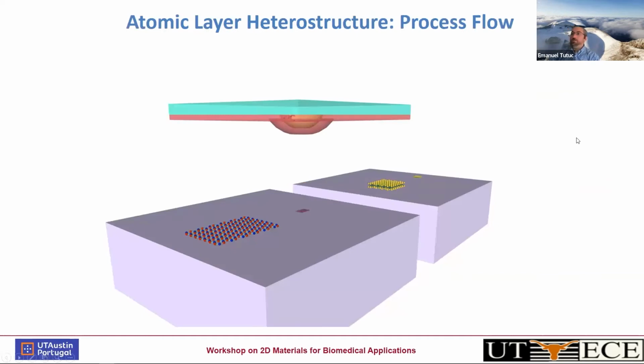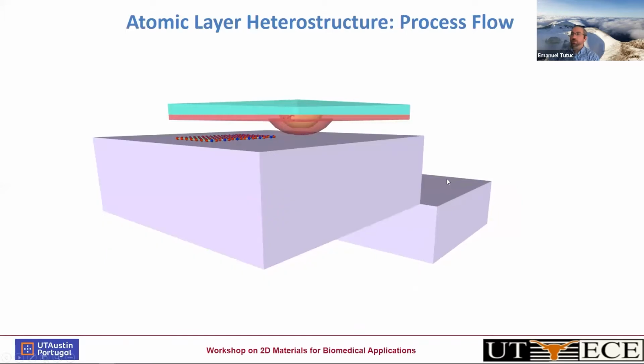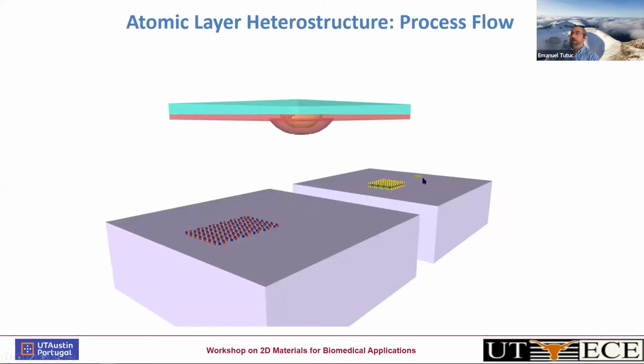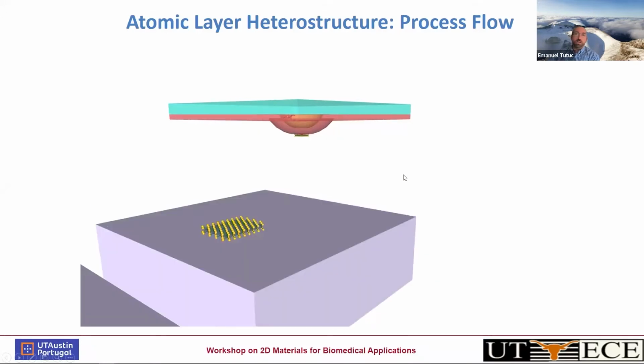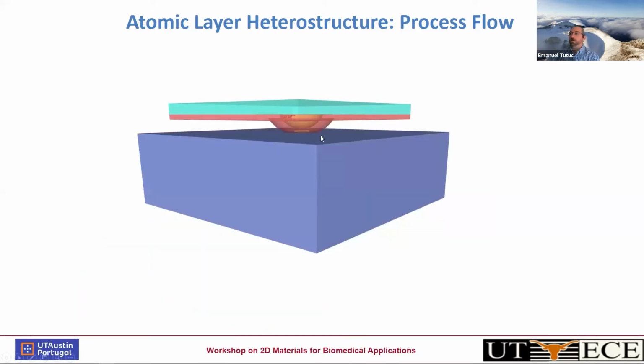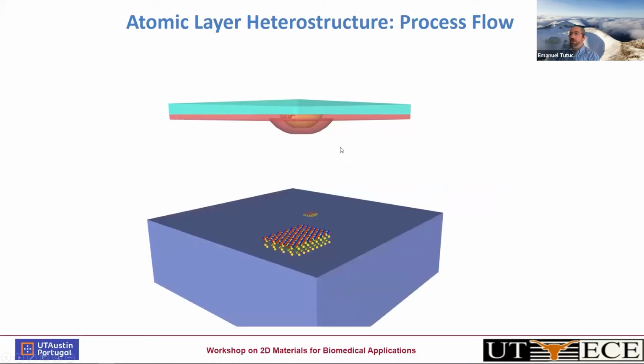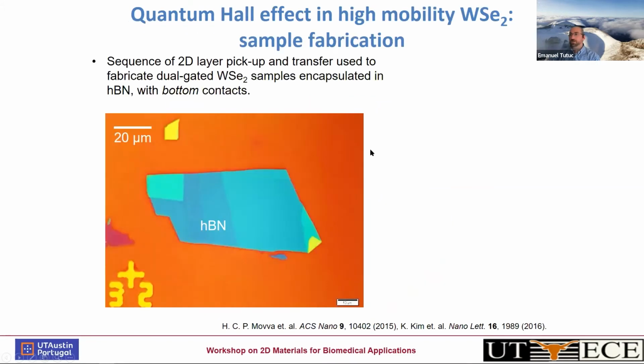So pictorially, let's say that we have identified the flakes as shown earlier. Let's say we start with hexagonal boron nitride, we land on, we pick it up, and then we go to a different location or maybe a different wafer which has a transition metal dichalcogenide. We pick that up also, and we can iterate this, and typically we iterate with a number of layers. And then when we're satisfied that we have actually picked up the layers in the desired sequence, we release them by changing the substrate temperature. And then typically electron beam lithography, metal deposition, and sometimes etching is also used to finalize the device.